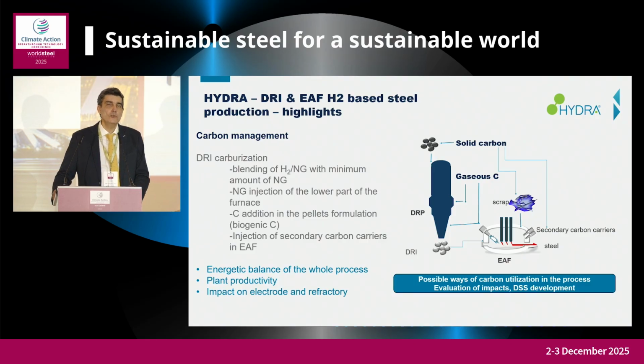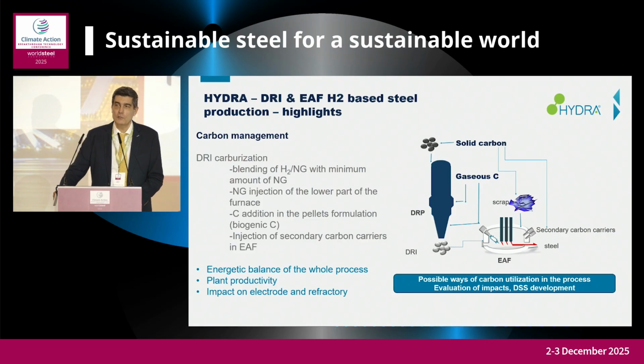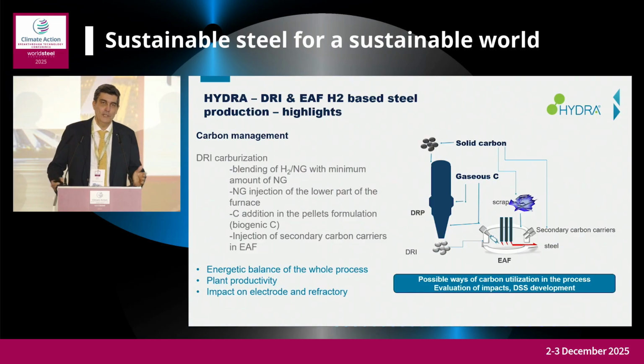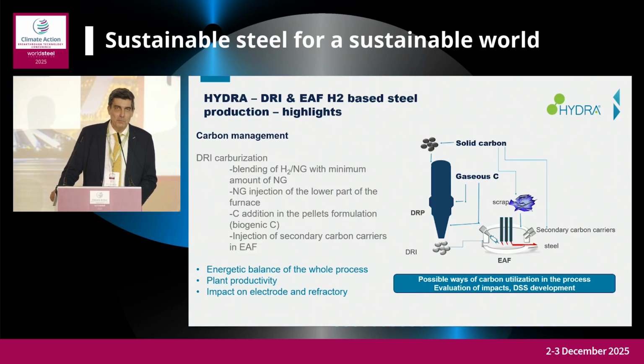Another important issue is the carburization of DRI. So if you produce with hydrogen, you surely don't have any carbon in your direct reduced iron. Is this a good or negative fact? There is a lot of analysis about this aspect. Personally, I'm not so sure that a totally carbon-free DRI is the best option for the melting step.